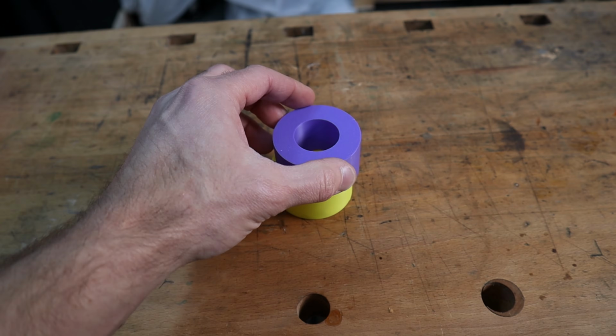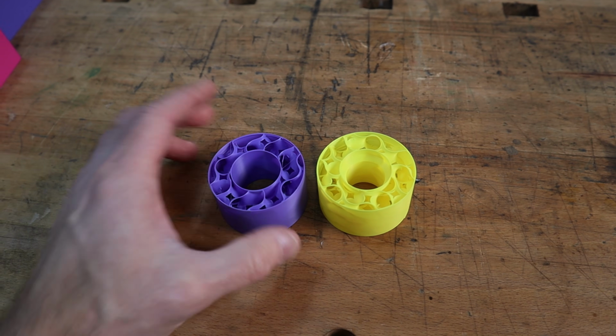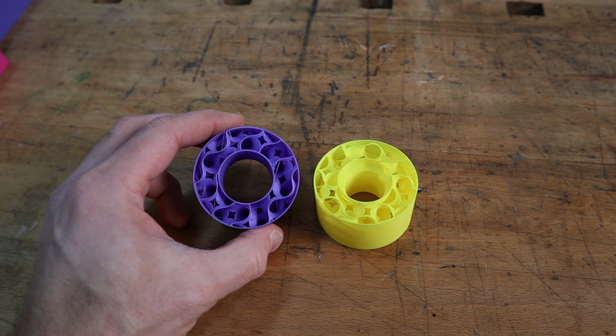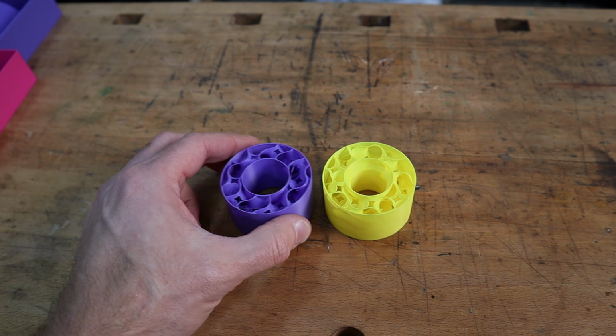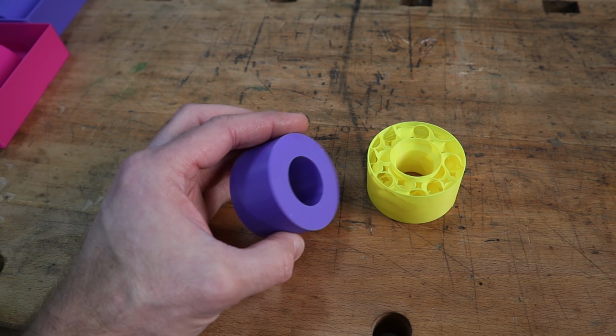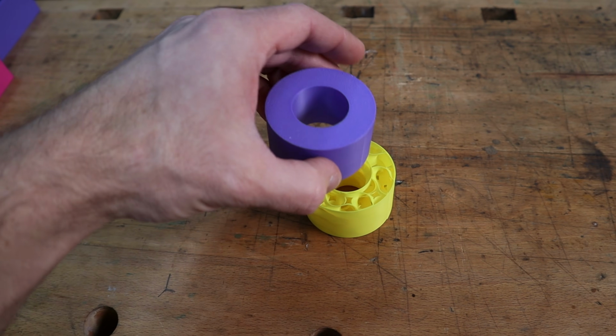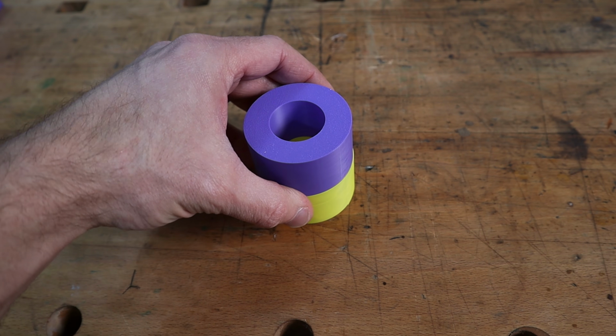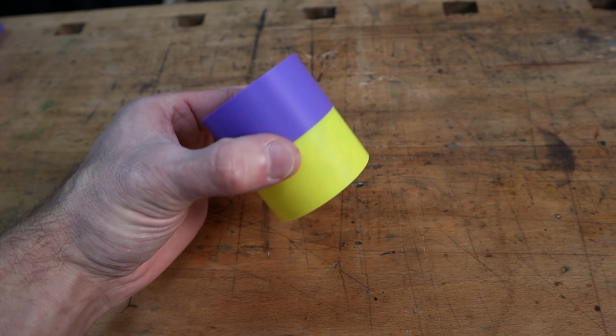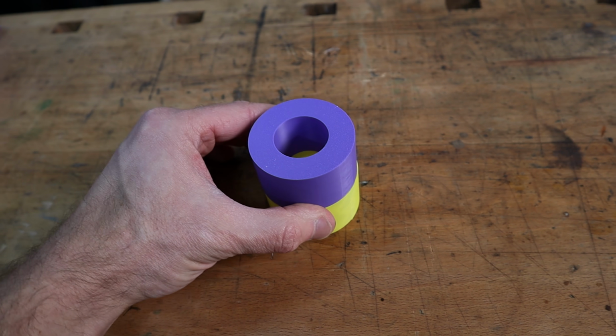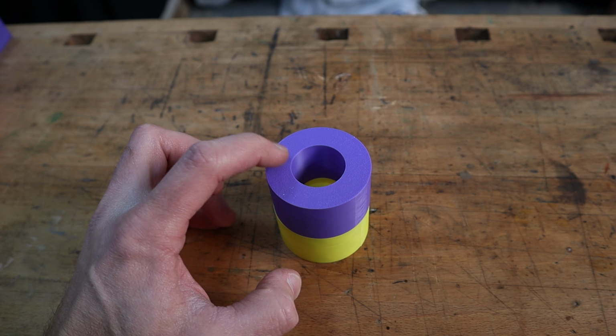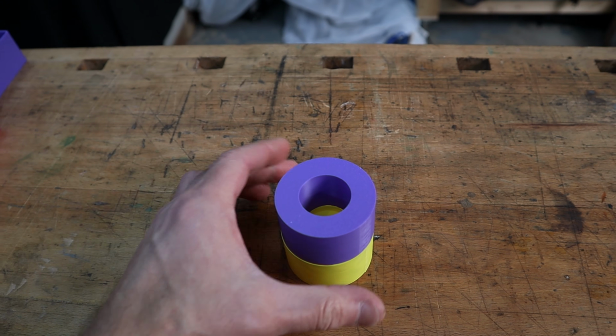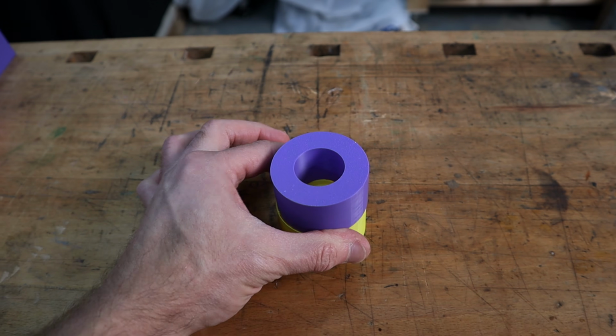So option number one is painfully simple. We have this two-part mold, with one wall, 5% gyroid infill, a 0.4 millimeter nozzle, 2 layers for the bottom, and no layers for the top. They're going to be glued together just like this, so it's going to be really clean. I'm just going to use super glue for this one, but you could use hot glue as well. And we'll glue on a piece of styrofoam as well to come up so that we can actually pour into this.